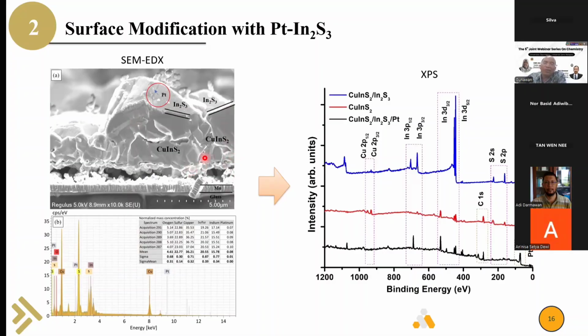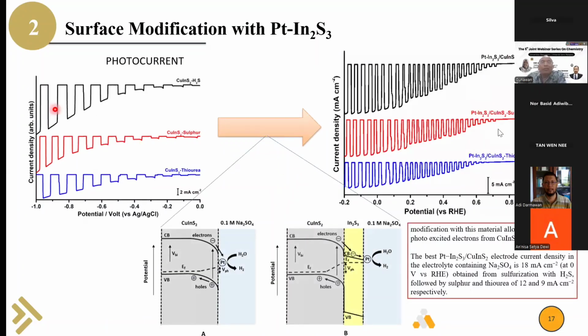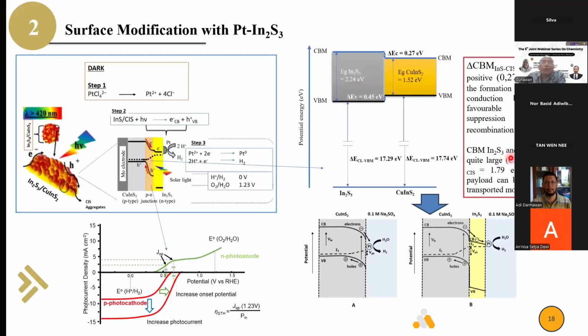Apologize, Prof. Gunawan, you still have around 2 minutes. Okay, I will continue. Make it fast. Okay. And this is the photocurrent for the copper indium sulfide covered with indium sulfide and platinum. So you can see here the sample still has a higher photocurrent, and the effect of surface modification also increases the onset potential in this picture.